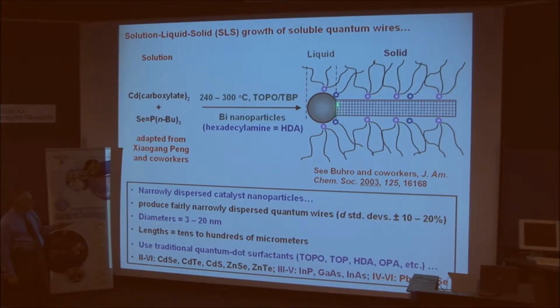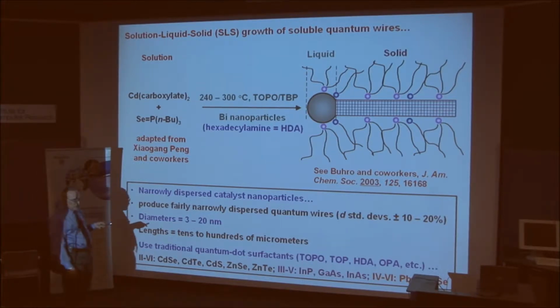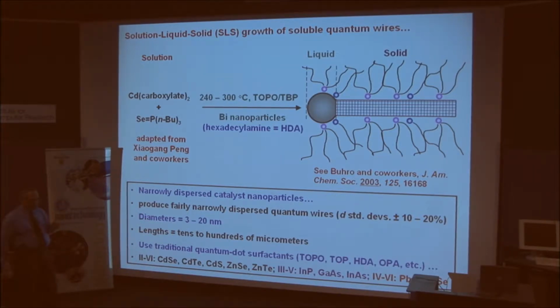But that's the only active crystal growth interface. So layer after layer after layer of semiconductor crystal is deposited here, and as that happens, the semiconductor wire is ejected from the droplet. So that's the part of the wire that grew first, and that's the part that grew last, and as long as we continue to feed precursors to the droplet, the wire will continue to grow. And because that's the only crystal growth interface, the wire develops a naturally approximately isotropic cross-section.